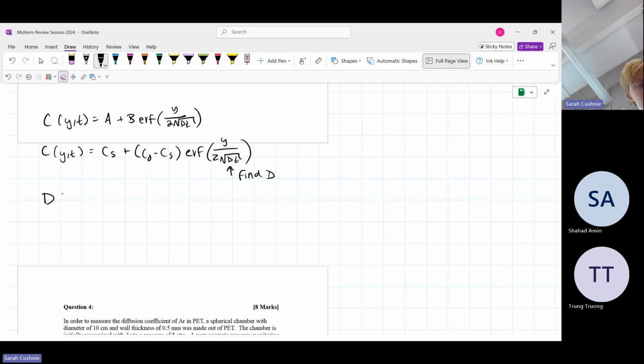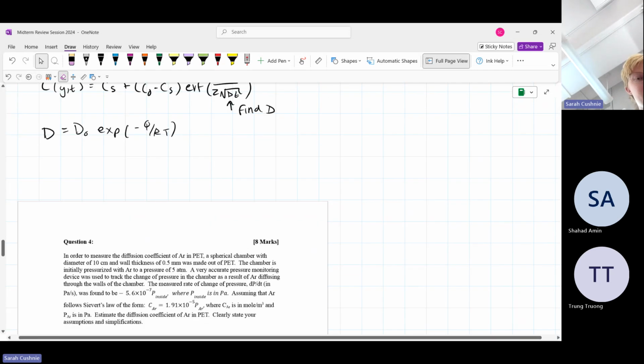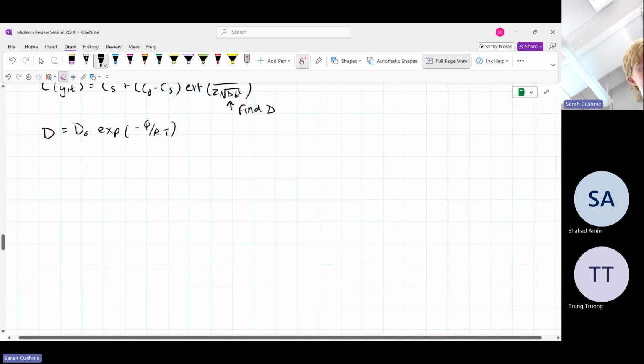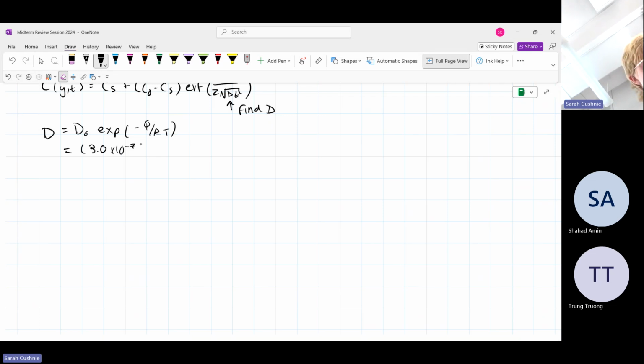We can use the equation D is equal to D naught times the exponent of negative Q over RT. And from here, it's just a matter of plugging and chugging. From the question, we know that D naught is 3.0 times 10 to the negative 7 meters squared per second, times the exponent of negative 100 times 10 to the 3 joules per mole, that's our Q value, over 8.314 joules per mole Kelvin for R, and 1273 K.